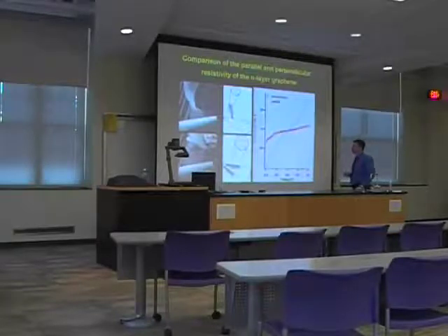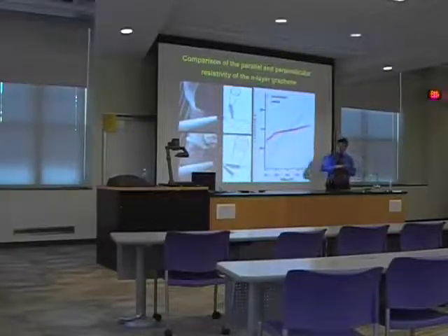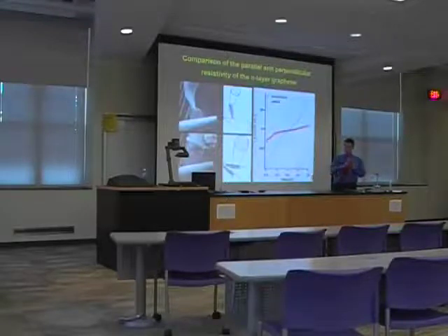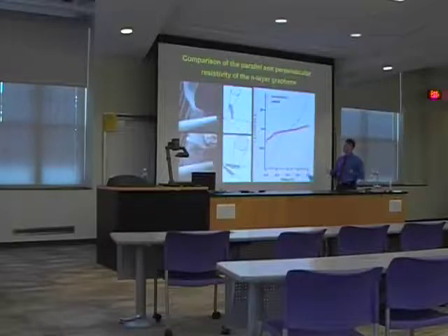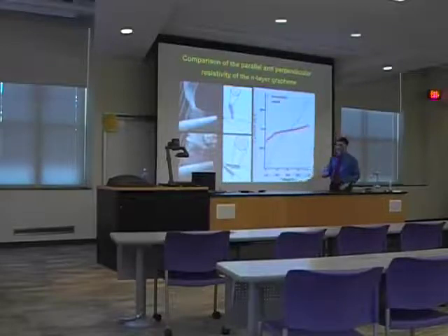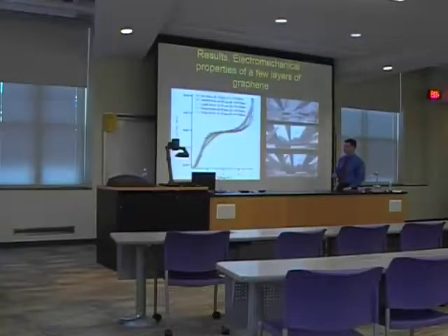What happens actually is that along the layer, electronic scattering is much smaller than across the layers. Electronic scattering between the layers of graphene is much more significant, and that's why we see this effect. But again, it's just preliminary results and very simple explanations at this point. Obviously, we need a lot of theoretical modeling and work of theoreticians on this subject.